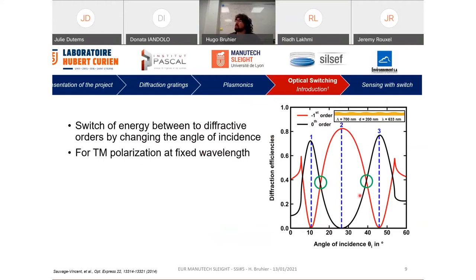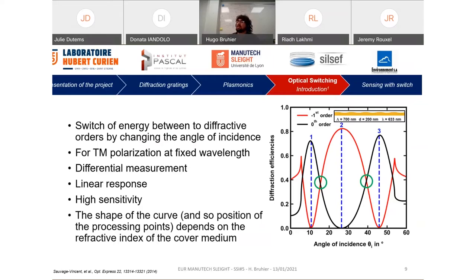Because the sensing measurements will be at these particular positions, we make a differential measurement between the minus first order and the fundamental order. Using differential measurements permits us to avoid some kinds of noise, for example variations in the intensity of the light source. Also, an advantage is that for low variation of refractive indices, we have a linear response of our method and a high sensitivity.